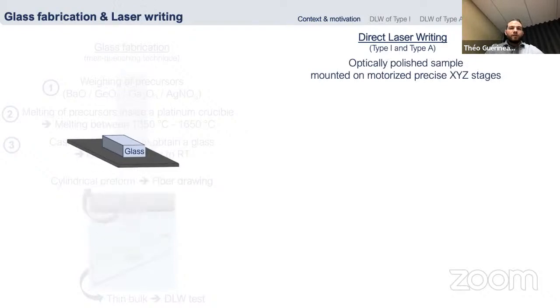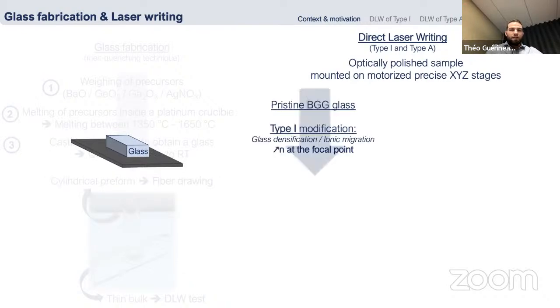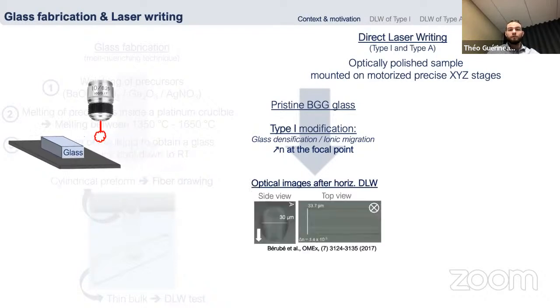Through the direct laser writing process, we need a sample that has been optically polished, which we mount on motorized precise XYZ stages. If we perform this type of irradiation on a pristine BGG glass, we go through a Type I modification. Thanks to glass densification and ionic migration, we increase the refractive index at the focal point. After a horizontal direct laser writing, what we observe is the formation of lines. On the picture on the left, you see the profile of this modification, and on the right, the top view of this line.